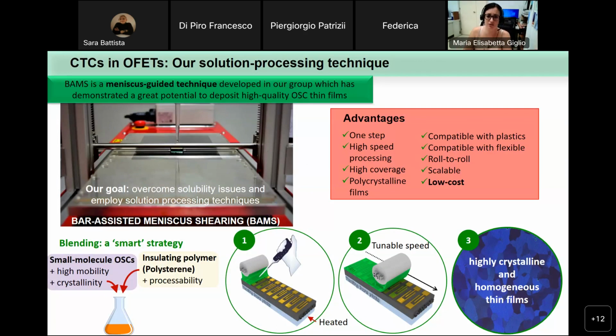So the advantages of this technique is that it's very fast. We can process the films at 10 millimeters per second or even more. It produces very crystalline films. It's compatible with plastics, compatible with flexible. It's compatible with the roll-to-roll mentioned before, and can be scalable.